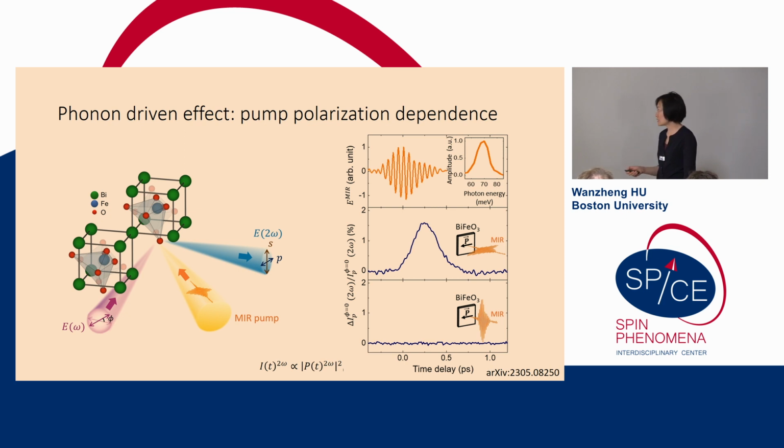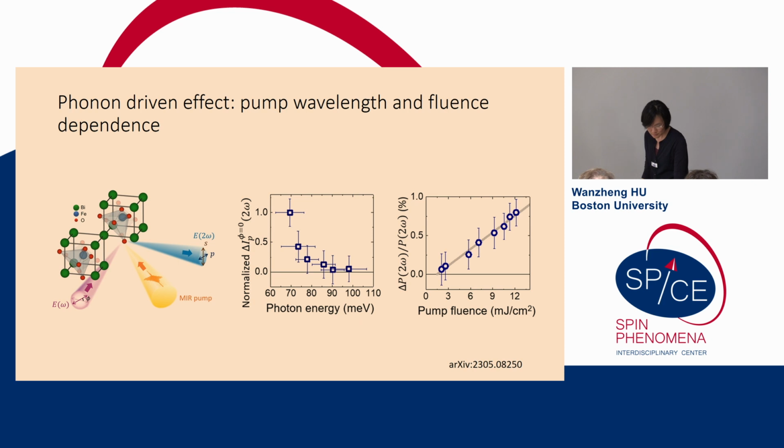So now, although the frequency is the same as the high IR frequency, it's orthogonal to the phonon resonant direction, so you would not excite any IR phonon. And in that case, indeed, we saw zero change of the second harmonic generation intensity.